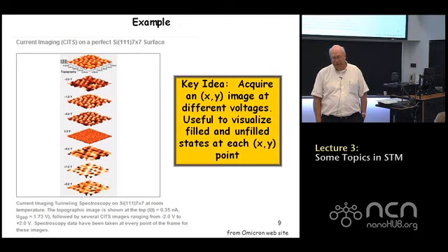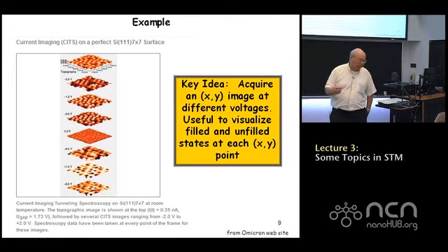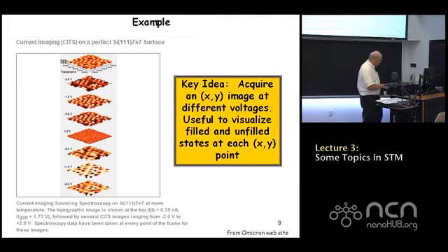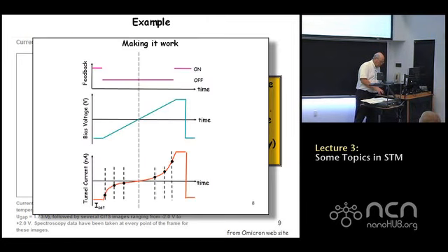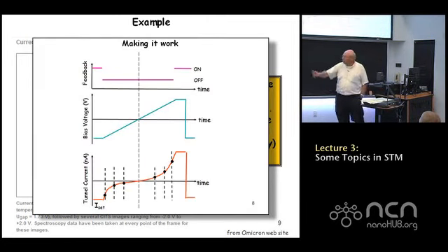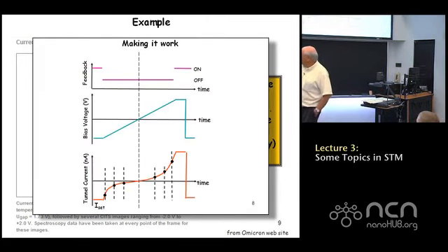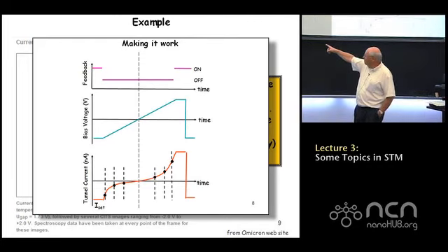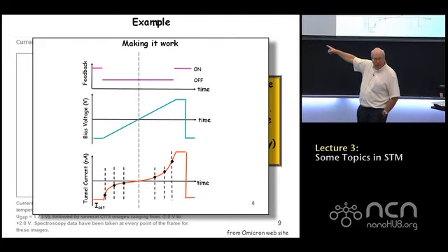By the band structure, I assume you mean the band gap. The band gap is 1.2 eV for silicon. If that's what you mean by band structure, then basically the IV curve will be reasonably flat around V equals 0 by plus or minus 0.6 volts. That'll reproduce the band gap in silicon.